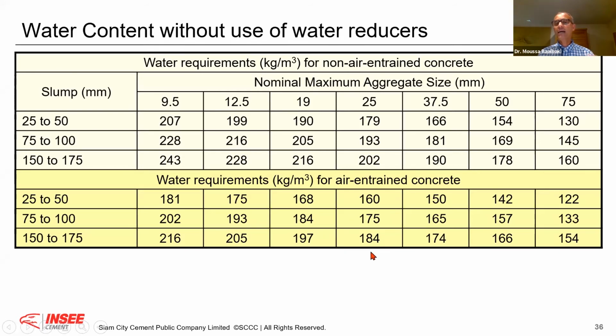Because in this case, I have entrained about 6% of air, and this is a ball bearing effect. It's like when you have fly ash in your concrete, you have very nice workability. That is really somehow the effect. Therefore, you can use this table also.